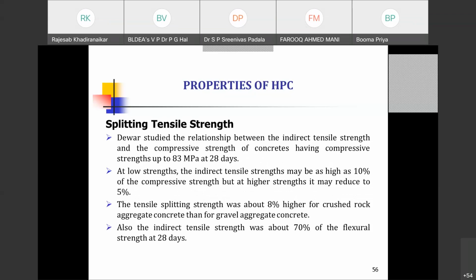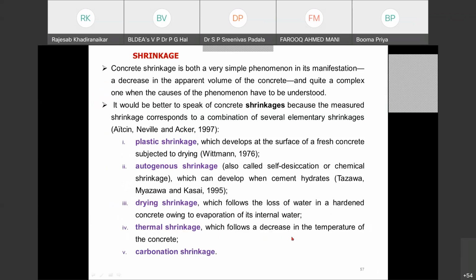Splitting tensile strength: they studied the relationship between the indirect tensile strength and the compressive strength of concretes in the compressive strength range of up to 83 MPa at 28 days. At a low strength, the indirect tensile strength was observed to be around 10%. But when it comes to high strength concrete, it was observed to be around 5 to 8%. The tensile splitting strength was about 8% higher for crushed rock aggregate concrete than for gravel aggregate. Also, the indirect tensile strength was about 70% of the flexural strength at 28 days.